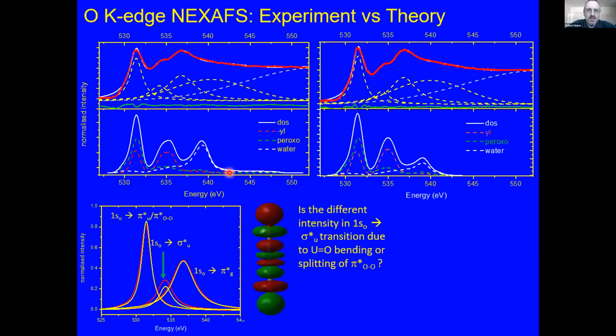And looking at the density of states, we can see that this peak has uranium contributions. This one doesn't. And it's only this one that has peroxy contribution. So maybe we should say that this is the pi star U and the oxygen peroxy pi star orbitals. This one is the sigma star U, and this one may be the pi star G, but it doesn't have any uranium contributions, so it must be just water.